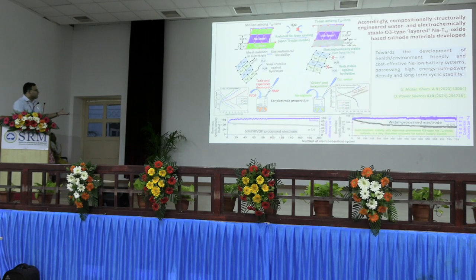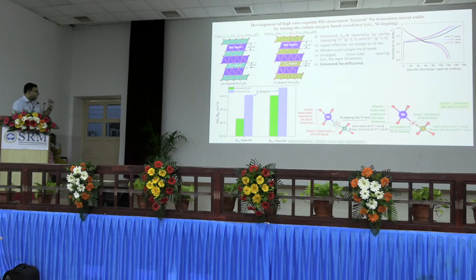So this is just one example, an earlier example. Now the performance is even better with some other modifications. It shows that not just air stable or water stable, we could actually make an aqueous processed electrode. That is, we did not use NMP and PVDF to make the electrode, rather we used water and sodium alginate to make the cathode, and the performance is very similar compared to the NMP processed one. This is up to 200 cycles, this is 750 cycles. So we could actually make aqueous processed cathodes with these water stable layered transition metal oxide cathode materials.